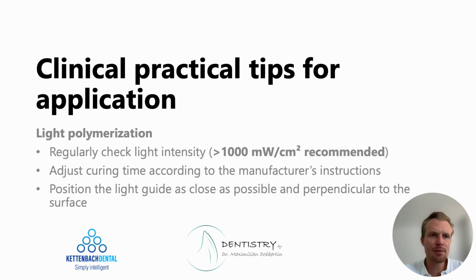Also, a clinical practical tip for the application is to use a light polymerization method with a lamp producing more than 1000 milliwatt per square centimeter, because then we can ensure that the light transmission and the energy transmitted is the best possible, because with a polymerization the material does a little bit of a light shift and a color shift, an opacity shift, which then leads to a reduced penetration of light through the restoration.